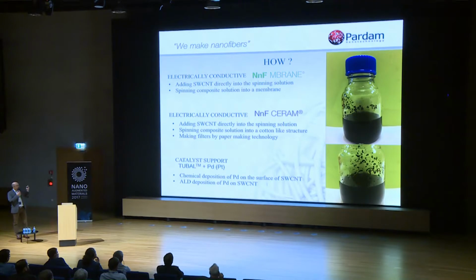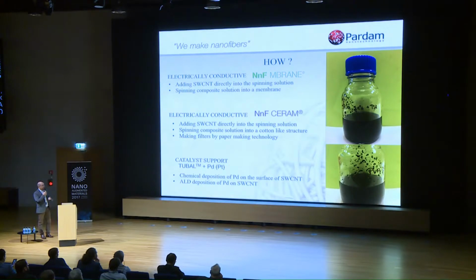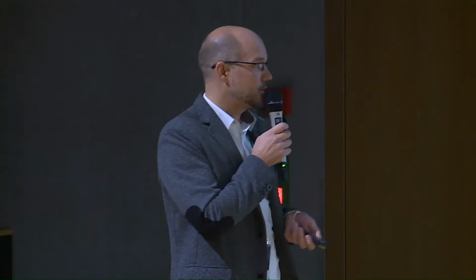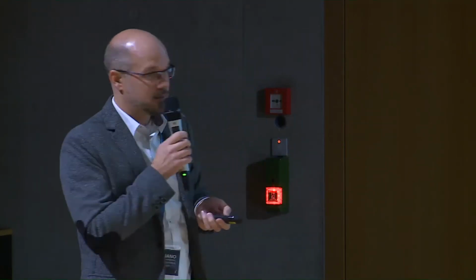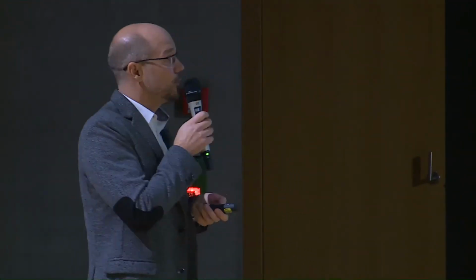We have encountered quite some problems. You see on the bottles the agglomeration of TUBALL nanotubes, and the reason is that we use quite a big concentration. So in the future we need to decrease the concentration of TUBALL in the solution in order to avoid the agglomeration. These were really first tests, and there is a lot of work in front of us. Catalyst support, chemical deposition of palladium on the surface of single-wall carbon nanotubes, or ALD, so-called atomic layer deposition of palladium. Those are pictures from initial results.